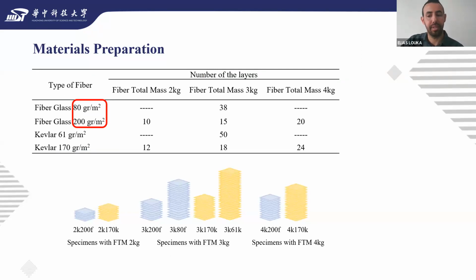3 different fiber total masses were investigated in this study. For the cases of fiber total mass of 2 and 4 kg, specimens of fiberglass of 200 grams per meter square and Kevlar 170 grams per meter square were prepared. For the case of fiber total mass 3 kilo, all type of composite were used. You can see the laminating structure of specimen about the different number of the layers in the figure below. The yellow color represents the Kevlar and the white blue represent the fiberglass.